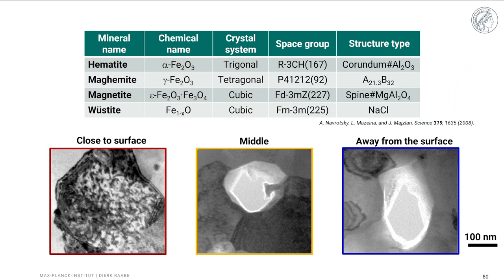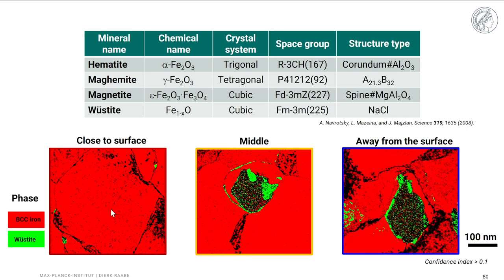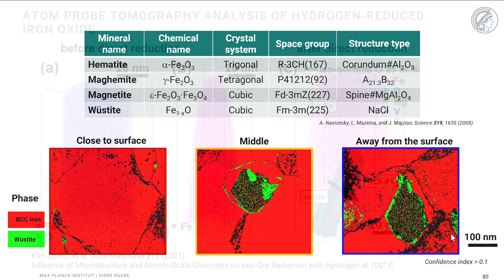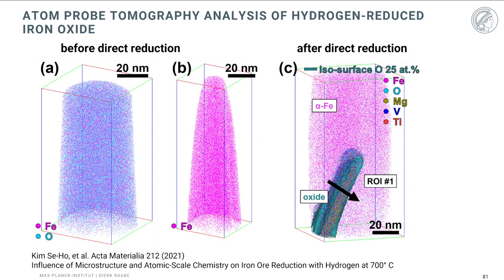If you look a little bit more into the detail, you can see that close to the surface of the material you have body-centered cubic iron, a few pieces of wüstite here and there. In the middle, you see around some of these pores actually a very high concentration of wüstite directly at the border to these pores. And we interpret this observation in terms of the high partial pressure of the water that has been formed inside of these pores and that could not leave the material because these pores are not percolating, so that this very high water pressure which builds up inside of these pores leads to reoxidation of the material back to the oxide.